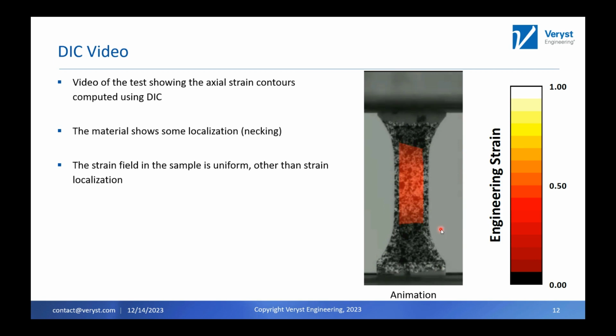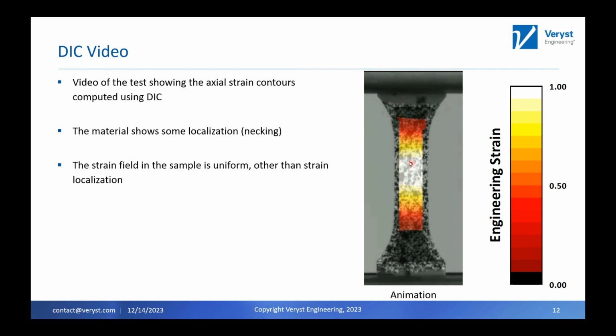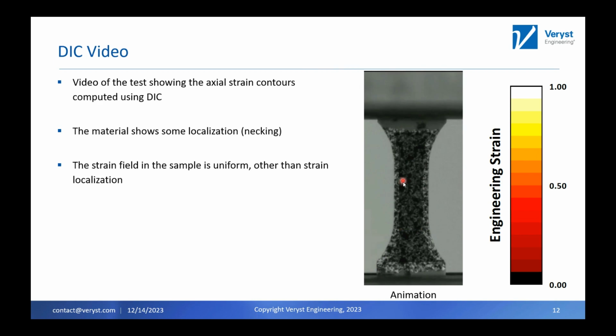And then we unload, we load up here. We're going to hold this strain for 30 or 60 seconds. Oh, in that case, we went to failure. We're holding the strain for 30 or 60 seconds, unload, reload, hold. And then you can see that there.